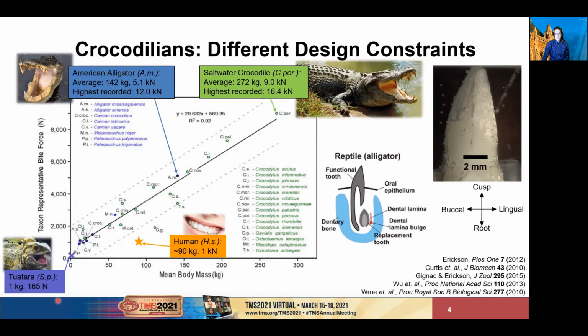I've also added the measurements for the tuatara lizard down here, which I will reference later in the presentation. You are probably aware that crocodilians are ambush predators, and when they snap their jaws shut on their prey, it causes a more dynamic load on their teeth, especially when they hit bone. The rapid loading condition and high bite forces put tremendous stress on the teeth. One way that crocodilians have adapted to that is to simply replace their teeth on an annual schedule, but then the enamel, which is only a few hundred microns thick, still has to function for a whole year. Our motivation for characterizing the enamel of these massive reptiles is to understand how it lasts that long.